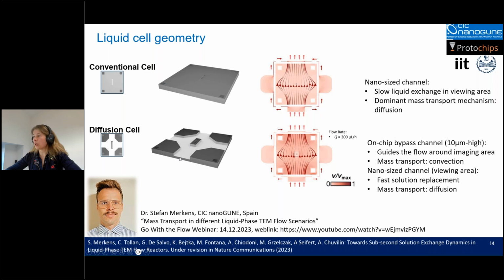So basically, we have this 10 micrometer deep channel within the chip, and the finite element modeling showed that the flow is very efficient, and it is efficiently guided in the channel around the viewing area. The dominant mass transport mechanism in this on-chip bypass channel is by convection, and in the viewing area, where we continue to have the nano-size channel, the replacement of the solution or of the electrolyte is faster